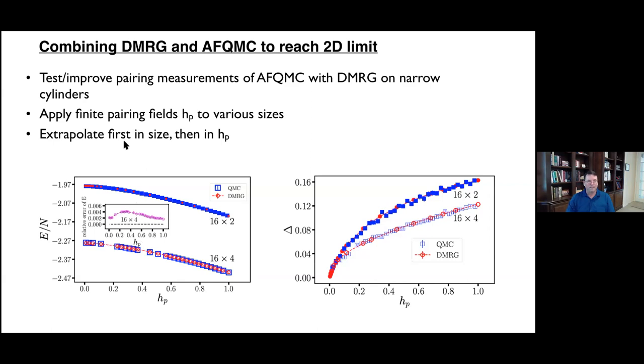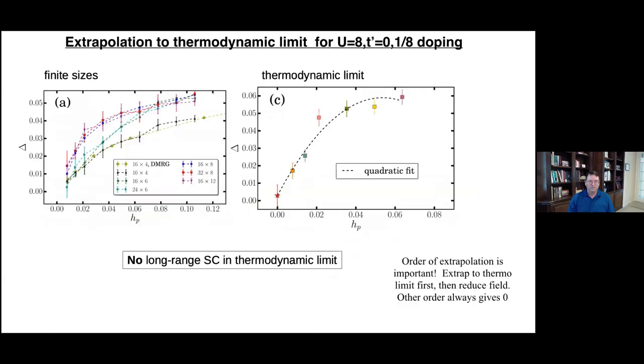And there was some development of the techniques for measuring things in the Monte Carlo, so we could measure things through energy measurements instead of property measurements, because the energy measurements were more accurate. But once we had developed those techniques, we found a very high level of agreement between the quantum Monte Carlo and the DMRG. Okay, then we could take the Monte Carlo to significantly wider systems, up to width 12.